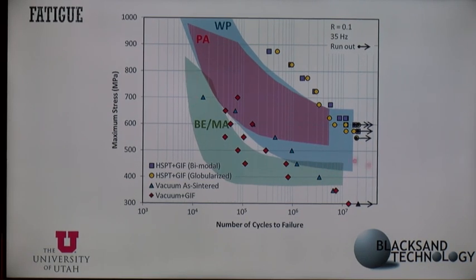As you can see, this is a typical curve. This green line right here is a typical area for what we previously were able to produce with vacuum sintering, whereas the red line and the blue line are what would need to be forged. You can see here these are actual data points of vacuum-sintered products, pretty much following directly in line with what we would see.